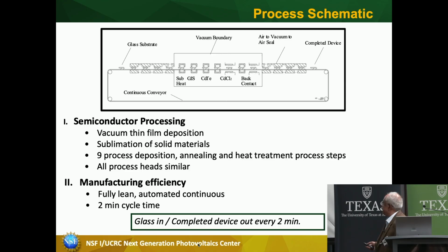And so glass comes in and gets heated, and then we deposit the N layer, the P layer, the cadmium chloride treatment, and put a back contact. We didn't invent the cadmium chloride process, but we kind of refined it to be this inline continuous vacuum process.